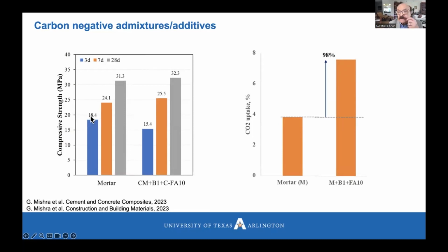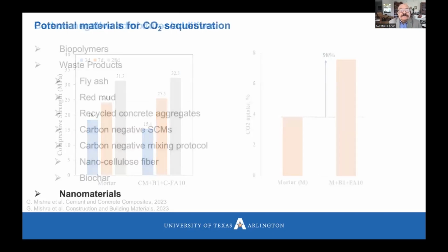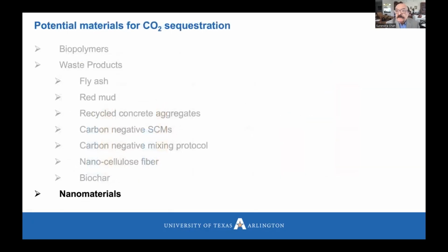And this is also mimicked in compressive strength. So compressive strength of 3, 7, and 28 days of carbonated mortar, and here carbonated mortar plus biochar and fly ash. So you can see that you can slightly increase the compressive strength, but the main thing is that you have captured CO2 and used a waste material called biochar. I want to talk about, can nanomaterials help in carbon capture, utilization, and storage.